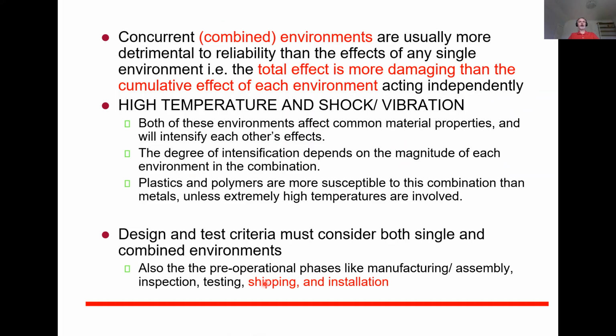So as was said a few slides back, the idea in the AEC standard is that you sum up the damages. So you have one damage coming from the thermal cycling, and you have another damage coming from the vibration, and then the total damage is this plus this. But unfortunately, in reliability engineering, 1 plus 1 may be something else than 2, or it's quite rarely 2. Sometimes it's 3, sometimes it's only 1.5. And that is the problem to really understand.